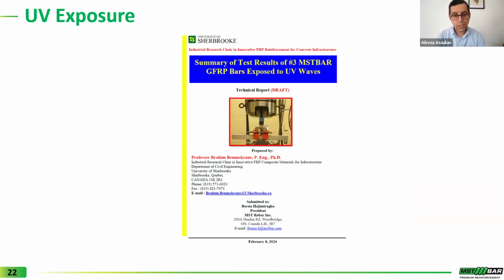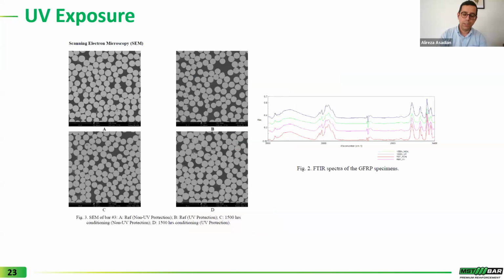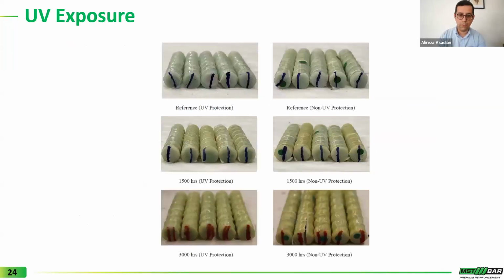So the effect of UV exposure is another concern for the long-term exposure of GFRP reinforced concrete. Again, we have done some load testing, some UV exposure testing with Professor Brahim Benmokrane. In this test, samples of MST bar were subjected to UV light for 1,500 hours as well as 3,000 hours, and then the scanning electron microscopy or SEM analysis as well as FTIR and interlaminar shear strength of the samples were measured.